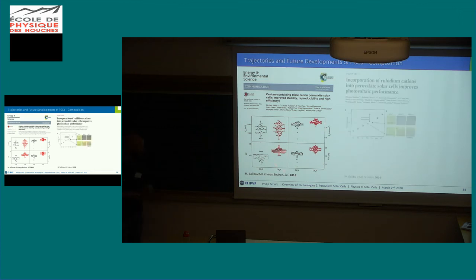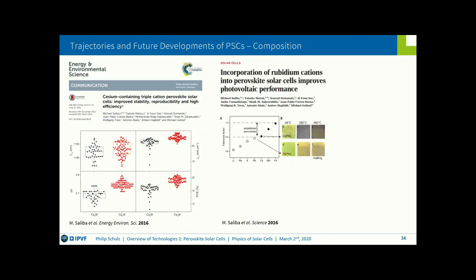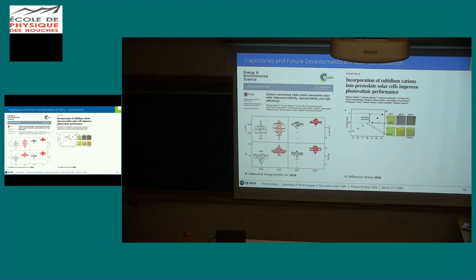as seen here for the device characteristics, and in red the cesium-containing devices. And the next step, and again it was Michael, he introduced and incorporated rubidium cations. So this is not really the classical way of making your baseline reference device, I want to say, because particularly, as you can see here, rubidium lead iodide is outside of this tolerance factor range, and it is presumably not integrated into the perovskite lattice.